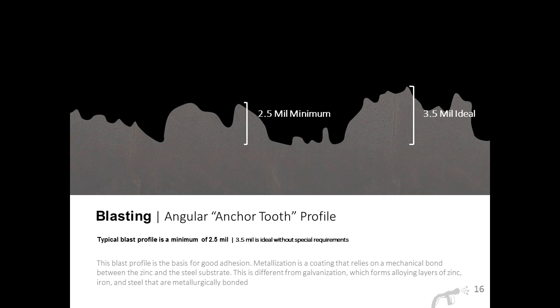A good roughened surface with pronounced sharp angular peaks and valleys provides a good surface for molten spray to adhere to. This mechanical bond is similar to other types of coatings like paint, which also rely on the surface area of the profile. What's really important to understand, though, is that this adhesion process is very different from galvanizing, which forms an alloying layer of zinc, iron, and steel. So when galvanizing, zinc is metallurgically bonded to the steel, essentially becoming a part of the steel itself. So it's not really a coating, and that's the difference. Galvanizing actually becomes part of the steel. Metallizing is different because you're relying on adhesion strength through the surface preparation of the profile.